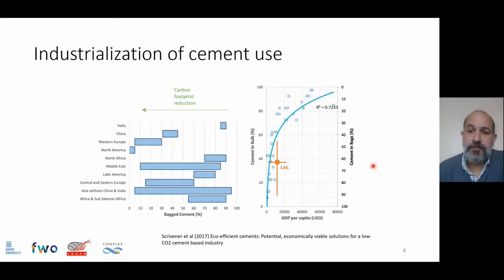Regarding the ratio between cement in bags and cement in bulk, when we see Latin America as a whole, we notice that the amount of cement in bags is much higher in relative terms in comparison with other regions. So we have this general trend worldwide. And for the average GDP per capita of Latin America, the amount of cement in bags should be much lower. And this is connected to the social structure that we have in Latin America, where social inequality and economic inequality is much higher than in other regions. This also affects the carbon footprint of the industry by increasing the demand of cement and concrete due to inefficient use of the materials.